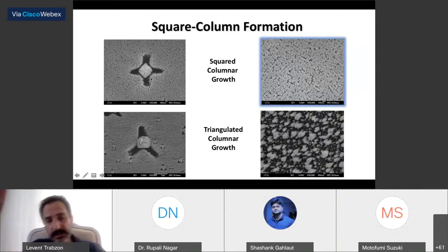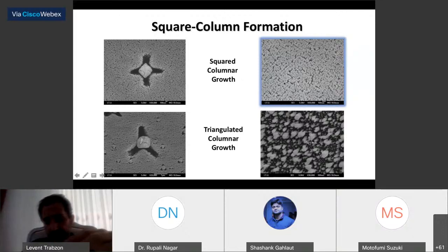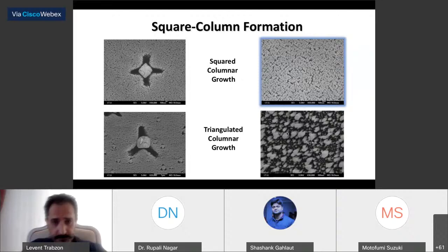But these are on the left-hand side. Those happened because of the dirts on the surface. On the right-hand side, that is the square-like columns, a columnar forest, and at the bottom, these are the triangulated columnar growth on the surface out of silicon.